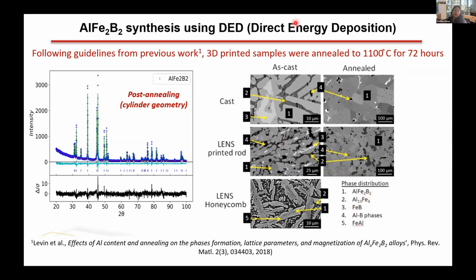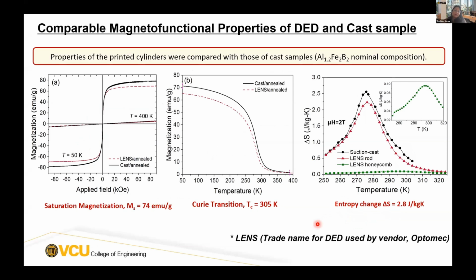Following our previous guidelines from studies on cast samples, the 3D printed samples were annealed at 1100 C for 72 hours. It was observed that the printed rods looked really good, but we couldn't get homogeneous samples in the honeycomb printed samples, which was unfortunate.